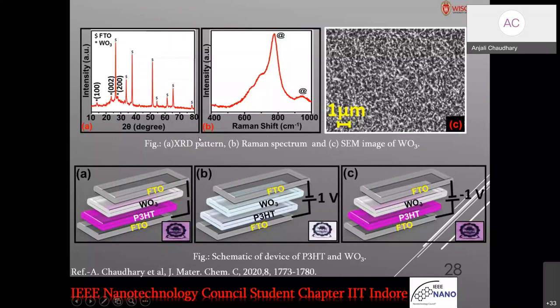And we have fabricated the device in a similar way, using FTO here. Tungsten oxide is grown on FTO and P3HT is spin coated on FTO, and then both of them are combined using some gel electrolyte in between. We see that there is a color change at 1 volt from magenta to transparent, and again at -1 volt it reverses to its magenta color.